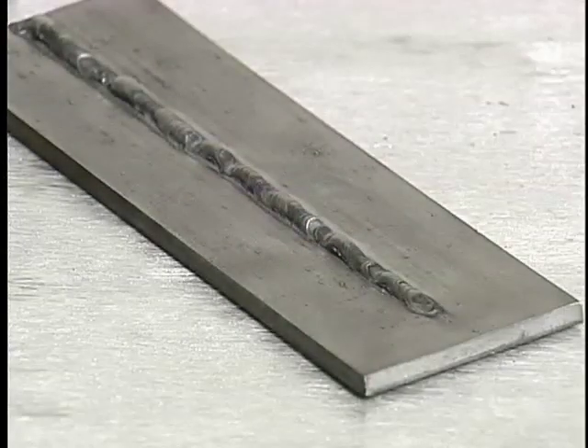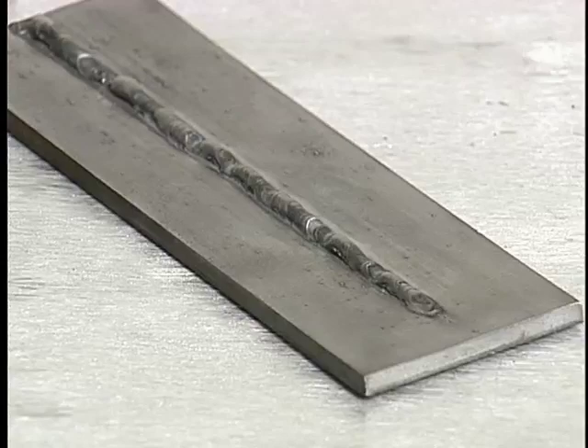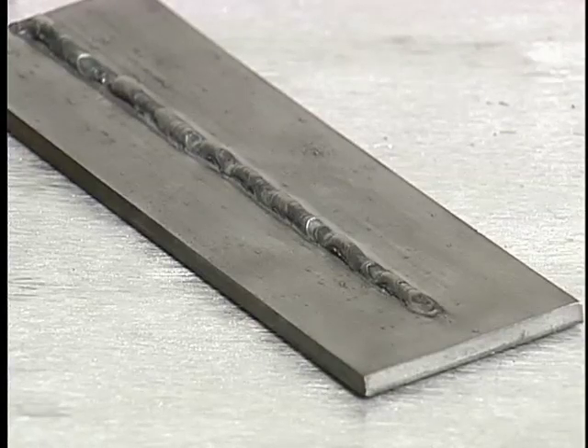If the amperage is set below the designated range, there is insufficient heat to melt the base metal, and the weld puddle is too small for proper control. The droplets forming on the end of the electrode may bridge to the weld puddle, periodically extinguishing the arc. And the weld bead will be irregular, with a crowned appearance and insufficient penetration.